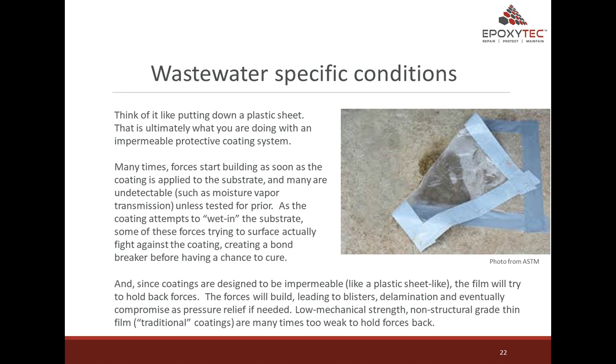As the coating attempts to wet into the substrate, some of the forces trying to surface actually fight against the coating, creating a bond breaker before it has a chance to cure. And since coatings are designed to be impermeable, like a plastic sheet, the film will try to hold forces back. The forces will build, leading to blisters, delamination, and eventually compromise as pressure relief is needed. Low mechanical strength, non-structural grade, thin film traditional coatings are many times too weak to hold forces back.